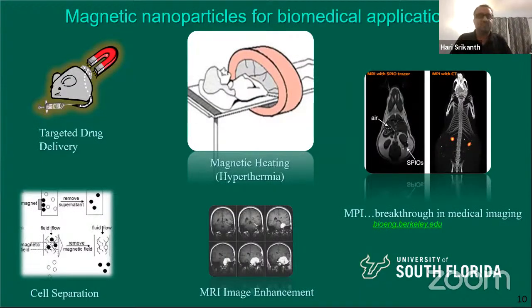Okay, so let's see, for example, where magnetic nanoparticles are being used these days for many biomedical applications. If you start from the left here, targeted drug delivery. It turns out that if you can take these nanoparticles and make them biocompatible by doing some surface functionalization, then you can inject it into the human body or into an animal, and using an external field, because it is magnetic, non-invasively, you can move it to an area where you want the drug to be delivered. For example, you can coat the nanoparticles with drug molecules and then locally guide them with an external magnetic field to deliver the drug. So in this case, magnetic nanoparticles are like ships. They're like navigational aids for transferring the drug inside the human body.